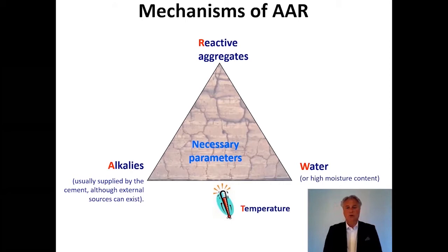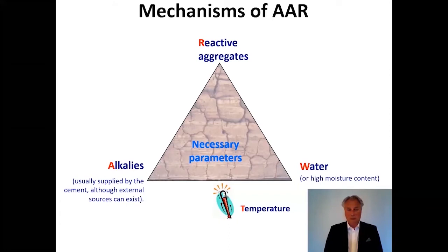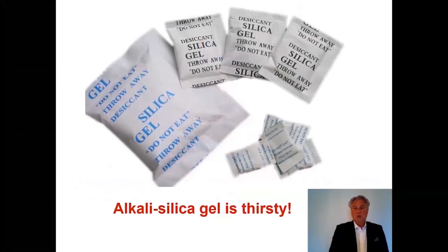If you lower the water content, like in indoor concrete, you will not have this reaction. And if you have the alkalis below a certain level, then the reaction will not occur either. The alkalis will be supplied from the cement, but could also come from external sources and even from the aggregates themselves. Additionally, increased temperature will also accelerate the reaction.